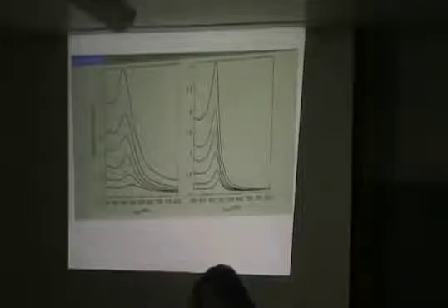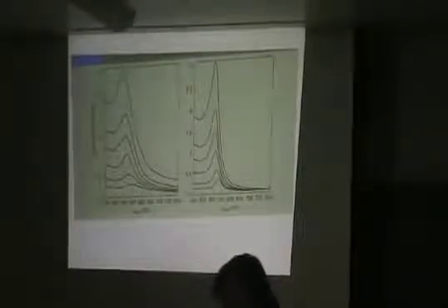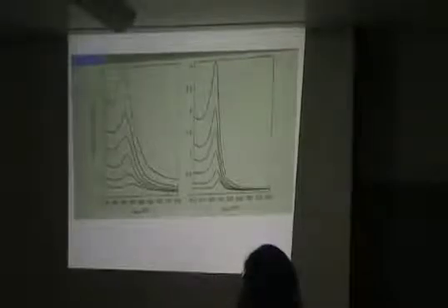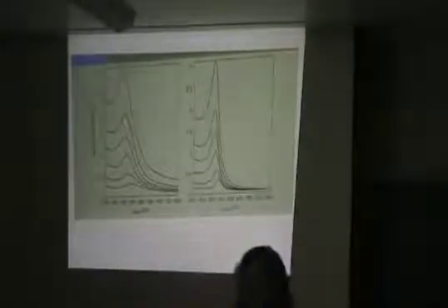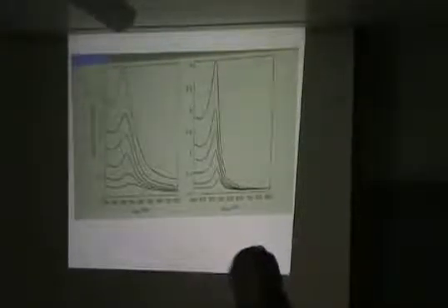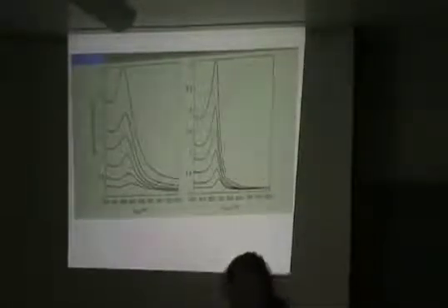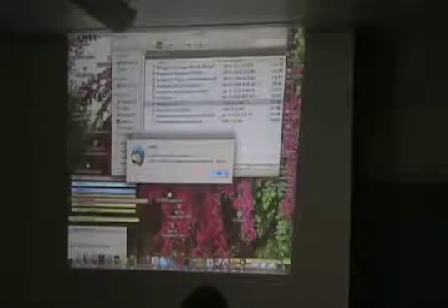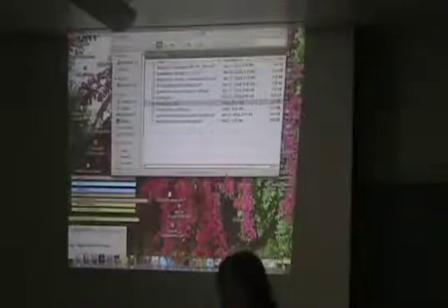Okay, now this shows a different one. It's too much detail, but I just want to tell you this kind of stuff exists, where on the left side they have taken experimental data for gold now in different shapes. Not just spheres, but oblate, etc., with different aspect ratios. And the right side is theory, again with different aspect ratios. You can look at this in more detail, and there's a caption which says what the aspect ratios were. But what I'm saying is people can now do these calculations and test some of it. And again, remember, this is only valid in a regime where the wavelength is larger than the size of the dot, which is very well obeyed here.